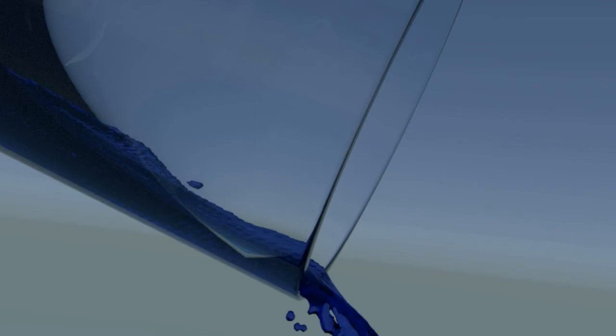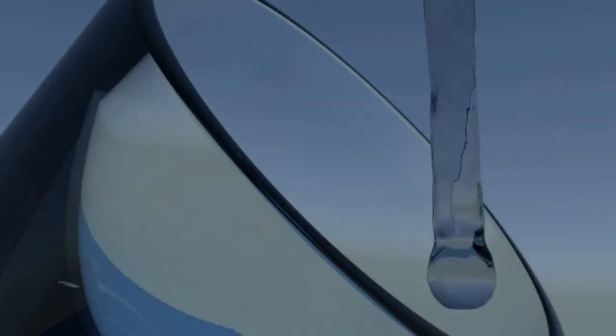Add a small amount of ammonia. Just enough to cover the gold mud. The ammonia will quickly change from clear to blue as it reacts with the dissolved copper that is clinging to your gold particles. Decant the ammonia. You can pour the ammonia into the bucket. However, if you do that, please be careful. The ammonia will react with the acid, and it may spit.